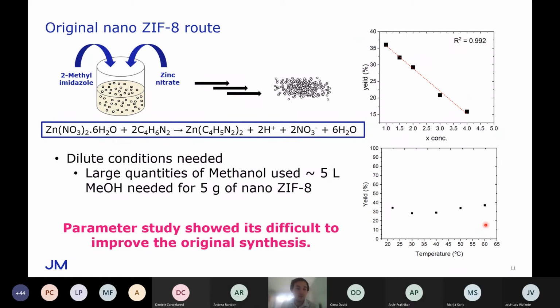When we first looked at this synthesis, we tried to intensify this reaction using standard methods such as increasing the concentration of the reaction or increasing the temperature, and we also played with many other parameters. However, as you can see, these parameters didn't really have an effect on the overall yield of the material. If we increased the temperature, it didn't affect the yield. And actually, when we increased the concentration of this reaction, it decreased the yield that we were making.